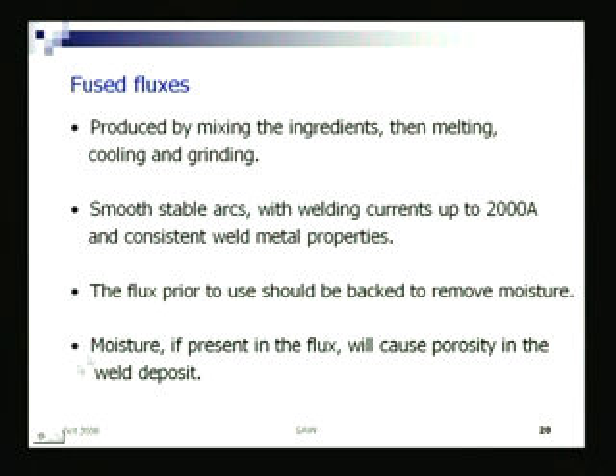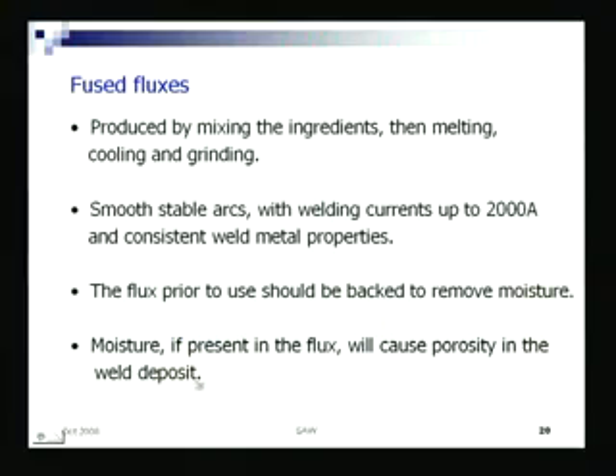Another important aspect is that the flux prior to use should be baked, to remove moisture, because as you know, moisture should not be there in a weld environment, as it will lead to hydrogen embrittlement, with hydrogen going into the microstructure. So moisture, if present in the flux, will cause porosity of the weld deposit as well as hydrogen embrittlement.